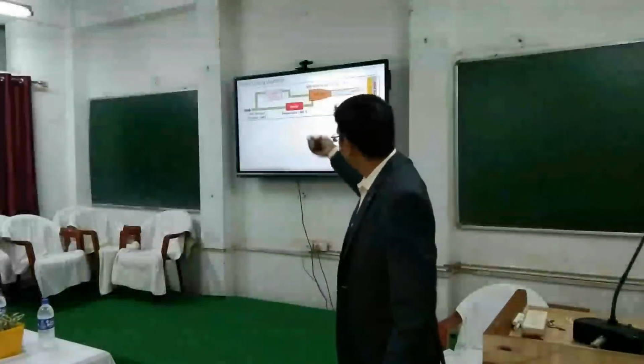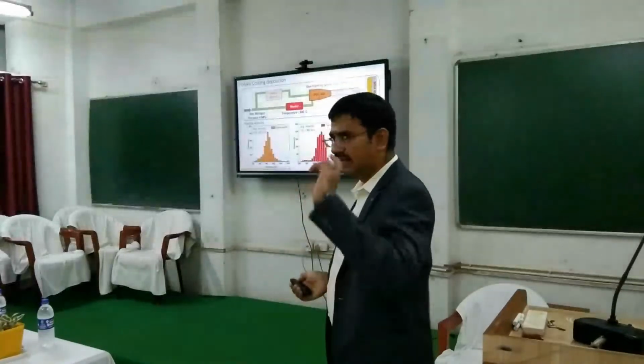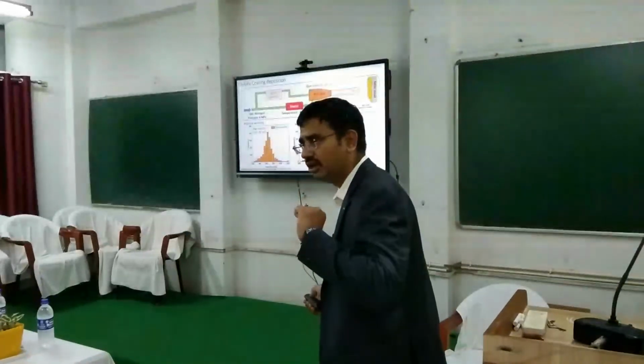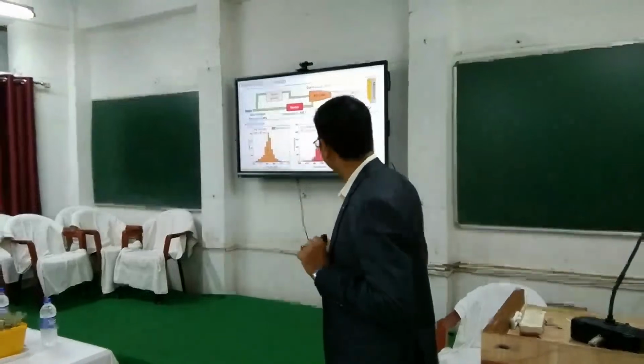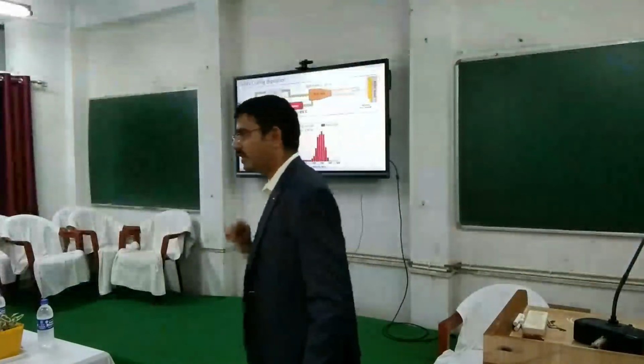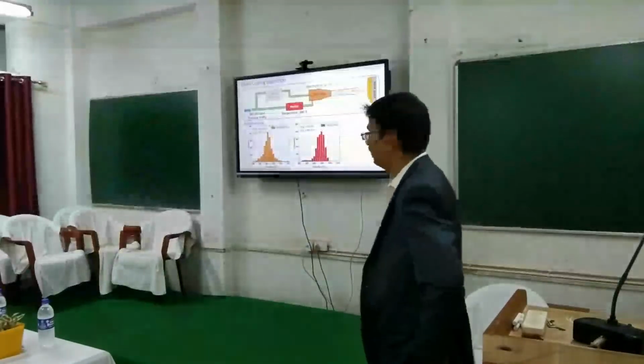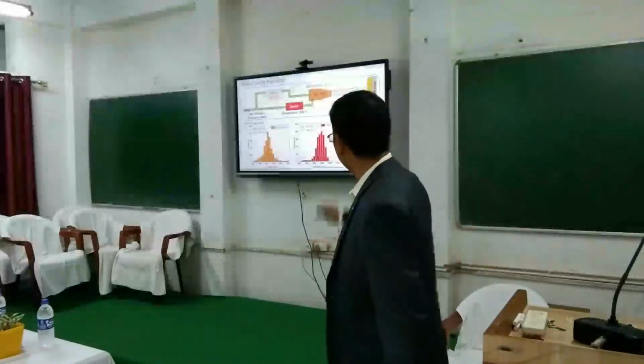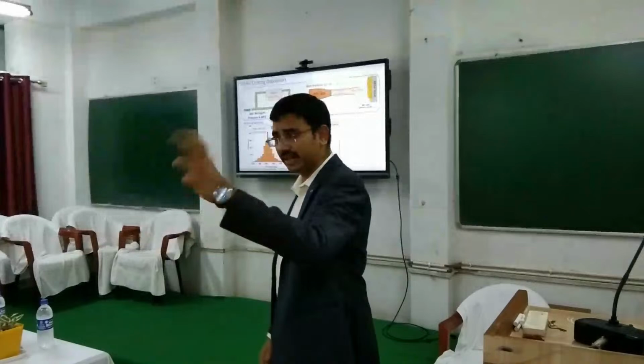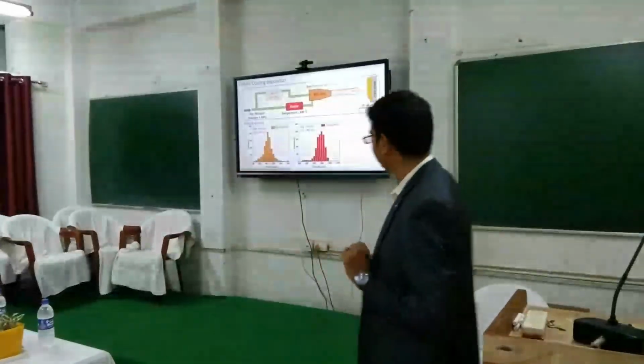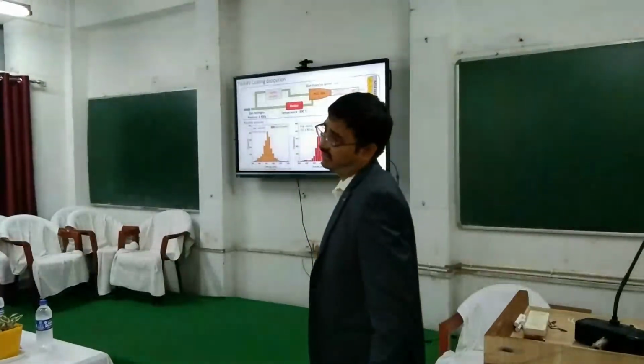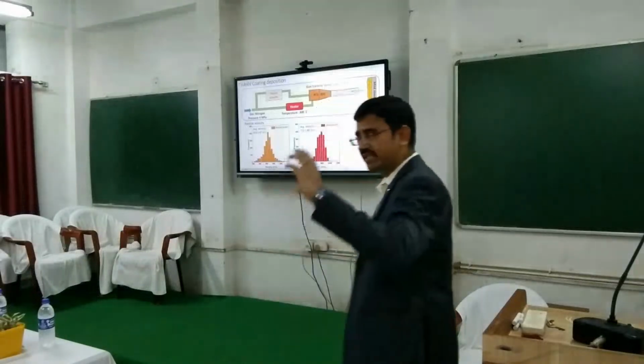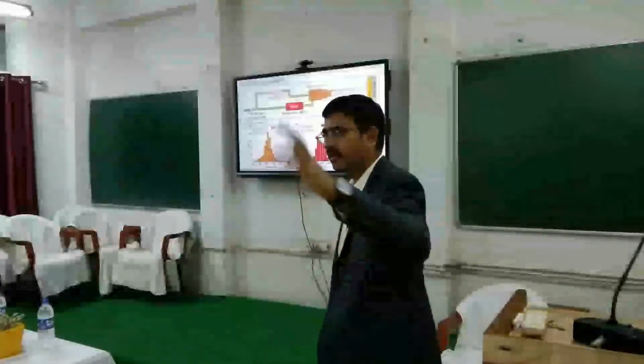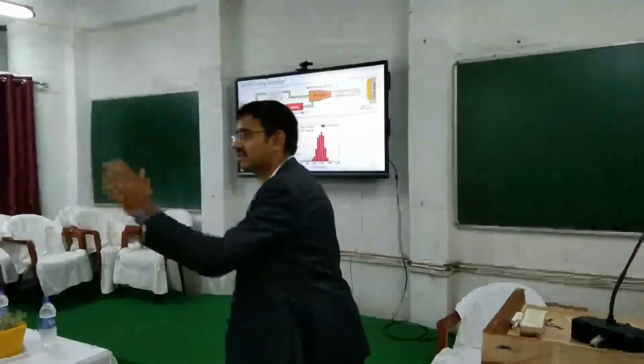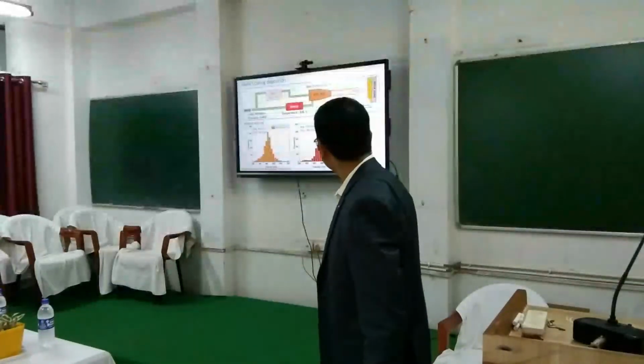We cold sprayed it using nitrogen as the propellant gas, and while spraying we measured the particle velocity using a particle velocity monitoring system. We found that the spherical powder particles were accelerated to an average velocity of 619 meters per second. For the same input spray parameters, the irregular powders, due to the irregular morphology and higher drag force in the free gas stream, were accelerated to 732 meters per second. So by changing the morphology for the same input parameters, you are getting higher velocities because of the change in morphology of the particles.